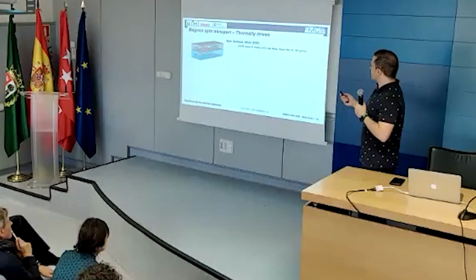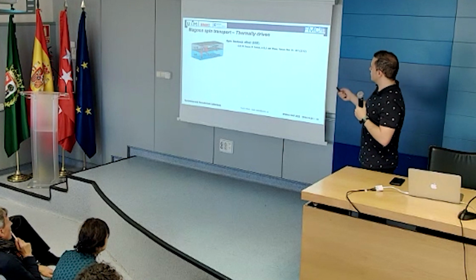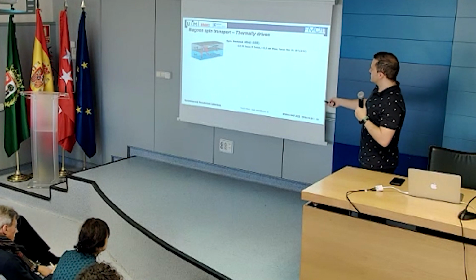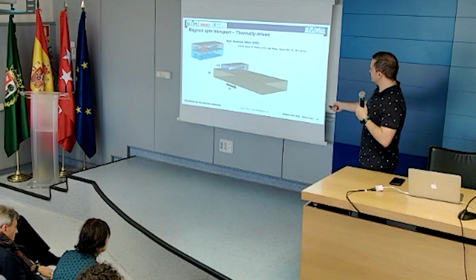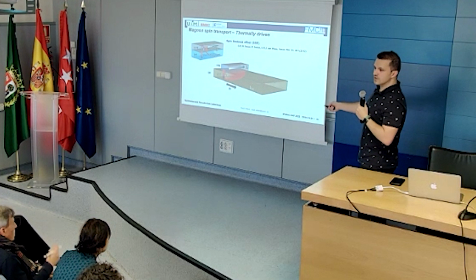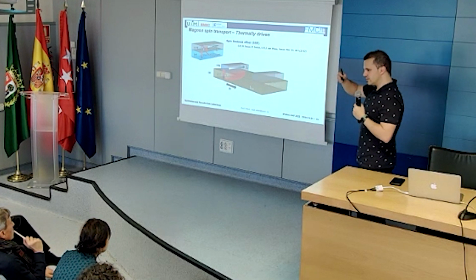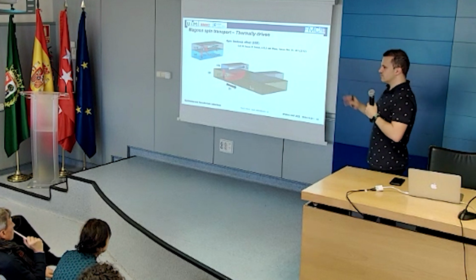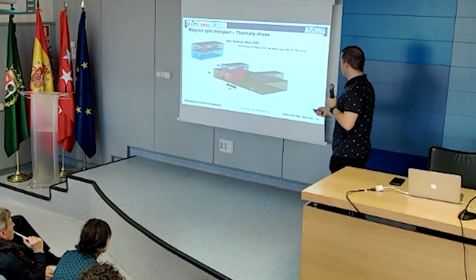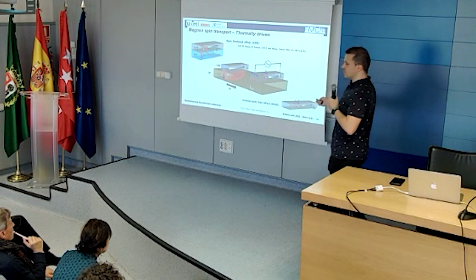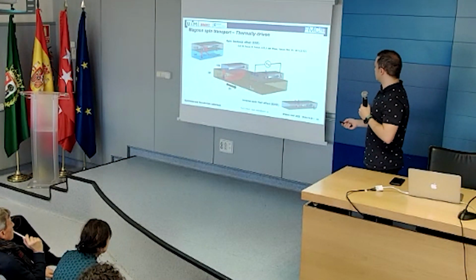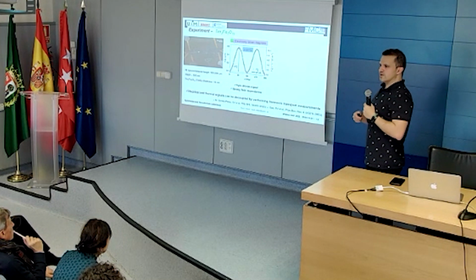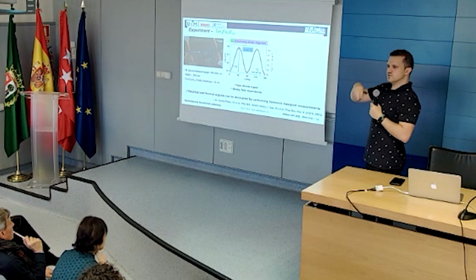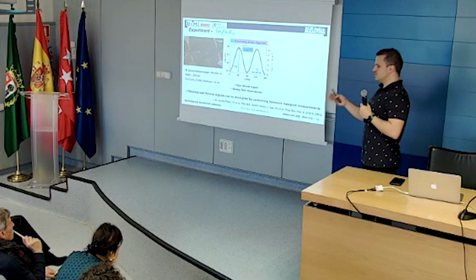But we have this as a spin, but you also have these thermal gradients that we were talking about before. You are generating also a thermal gradient at this interface, because you're running current. So now you forget about the spins at the injector, and you get this thermal gradient. This also drives magnons, because a thermal gradient in a magnetic material leaves a non-equilibrium profile of magnons. So this will be diffusing away and be also collected at the detector, via the inverse spin Hall effect. So now via these harmonic measurements, we can decouple the spin-driven signal, which will be in the first harmonic, and the thermally driven one, which will be the second harmonic.